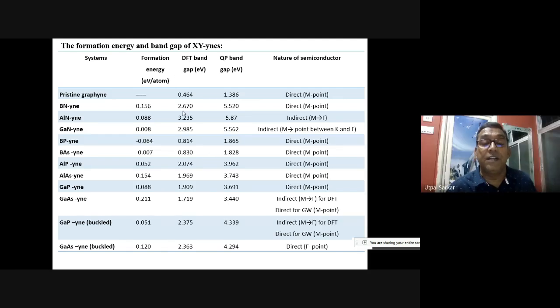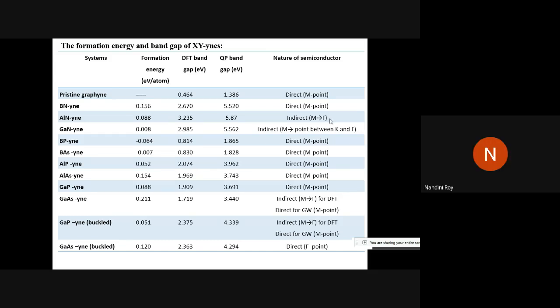This is the DFT band gap. We have also done this quasi-particle band gap, and you see when we enhanced our calculations, the model of calculations, though it is time consuming and computationally expensive, these quasi-particle band gaps are very close to the experimental results. So we have done it for all these materials, and it is basically increasing in nature, because only DFT calculation underestimates the band gap, and it is clearly visible from here. What is interesting here is that